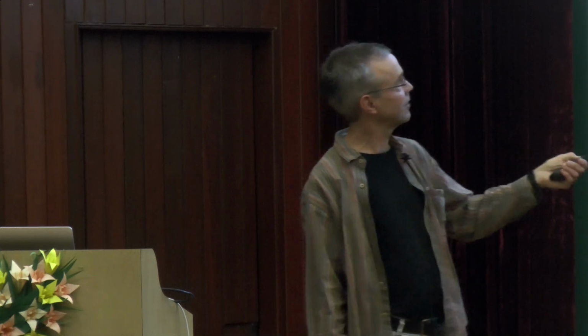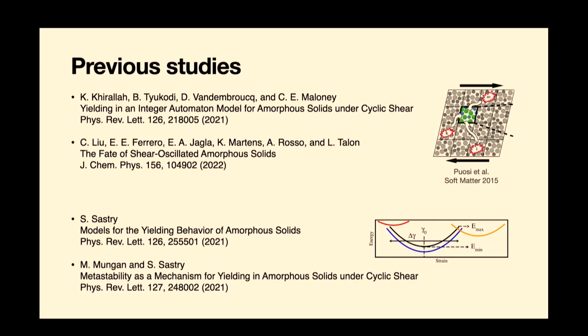These are the two mean field type models. This first one ignores the stress propagation, so it does have similar effects to what we've seen, but it doesn't have a genuine dynamical transition because the system always goes to a frozen state, an elastic state. This system has a sort of phenomenological version of the stress propagation in it, but doesn't actually represent oscillatory strain. It's a sort of simplified model that in some sense coarse grains from one period to the next. So we want to do something that is more in that vein of a mean field elastoplastic model, but that explicitly also has the stress propagation in it that results when something yields locally because that perturbs stresses elsewhere in the material. Okay, and do you see these kind of pings here?